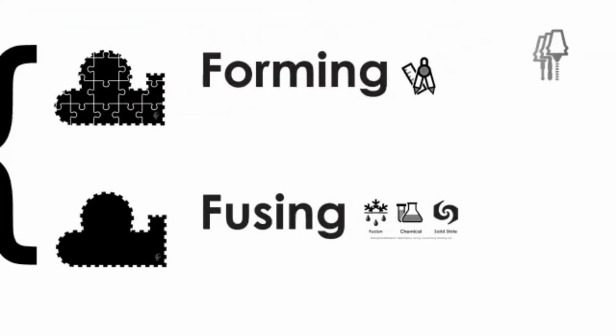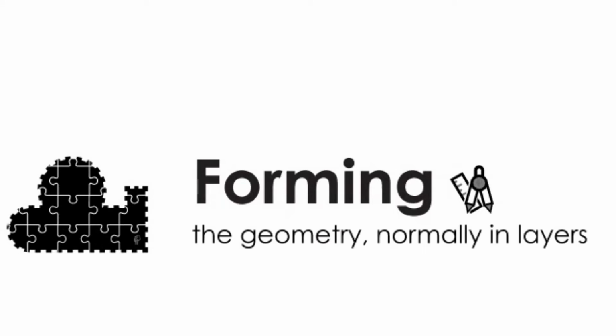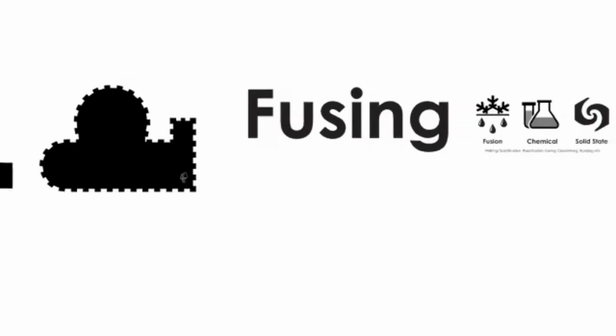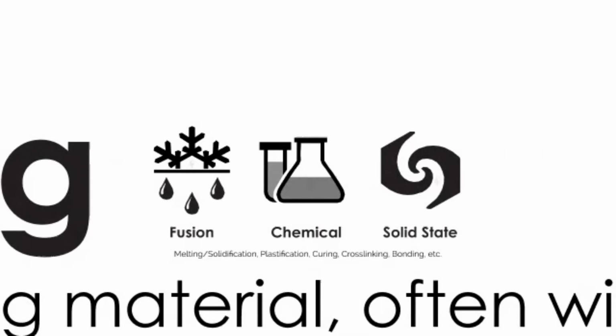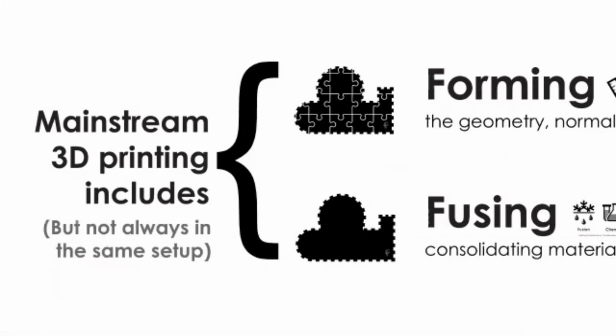But to be on the same page, when I talk about forming, I'm talking about creating a shape. And if you look carefully, you can see we've used puzzle pieces to represent this forming, geometrical shaping, if you will. Normally, forming happens by layers, right? Cross-sectional layers through a part. The fusing step is a consolidating step. So I use fusing in a broad sense. Often it uses heat, but not always. Things can be fused chemically or using solid state methods, and different additive techniques rely on different things. But this forming and fusing, those are the primary activities of additive, and they're not always done in the same step. You might have something like a fused filament fabrication or FFF process that prints a form with metal powder bound in plastic, and then as a second step, have to go and sinter that, right, in an oven to be able to get to a metal part that's mostly dense.